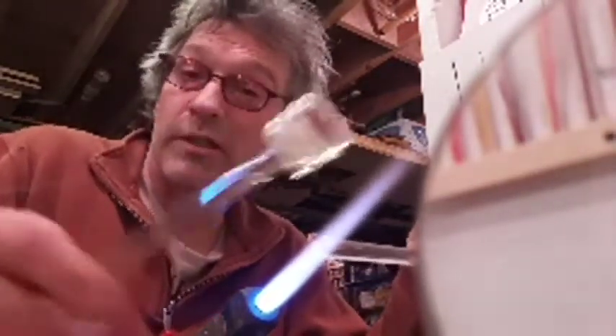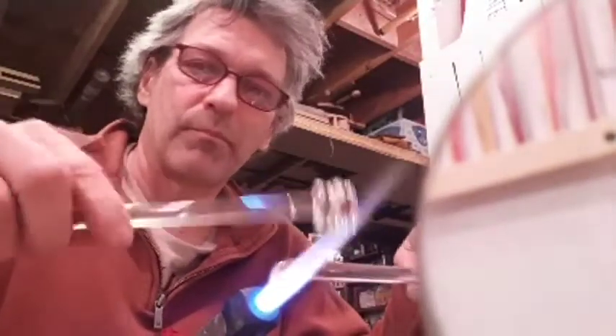But let's pick up the silver. See, it just turned orange. That's the right heat to pick up the metal without vaporizing it. There it is. So sometimes that last little piece of rouge paper that keeps the leaves separate is stuck to the piece, and then that just burns off. If you just heard it go foop, or saw a little flame down in the corner here as I picked up that foil, you can kind of smell it.